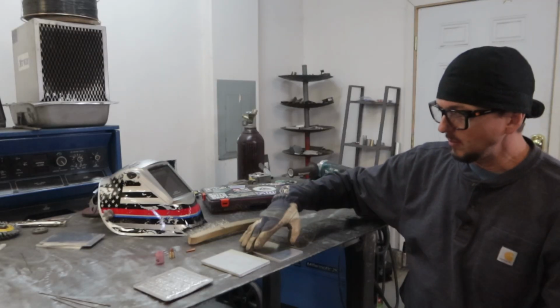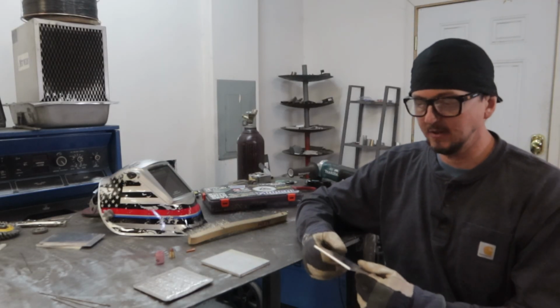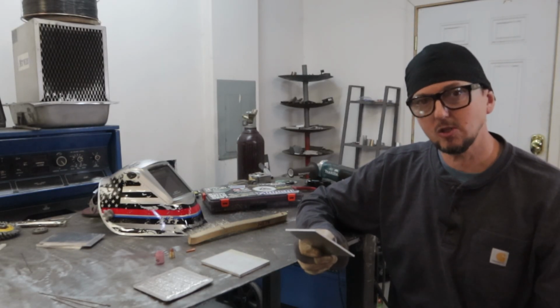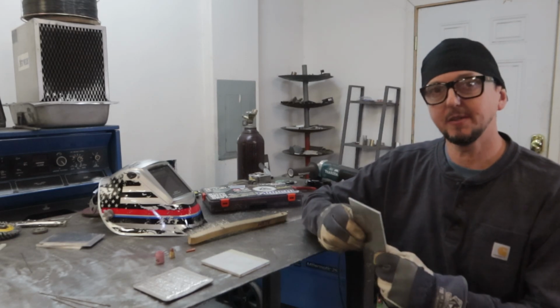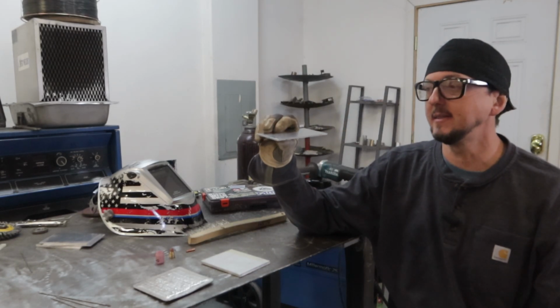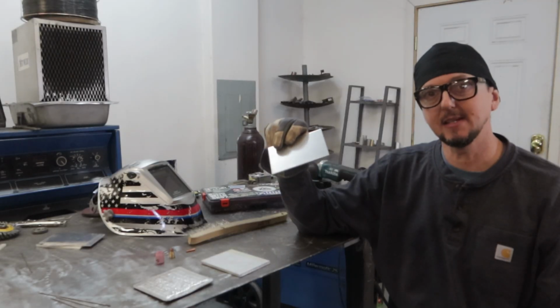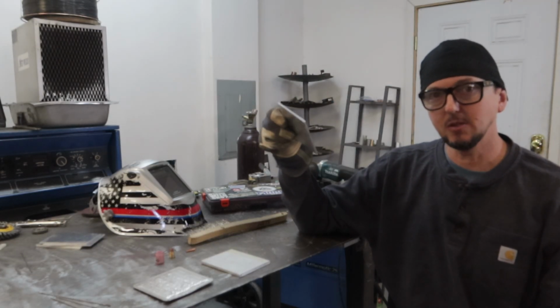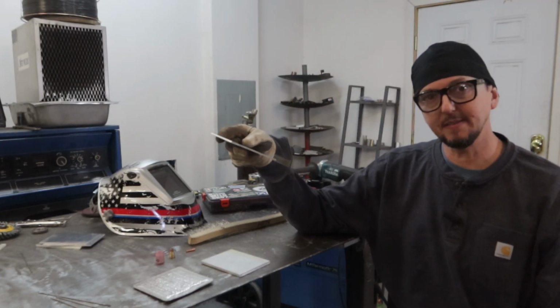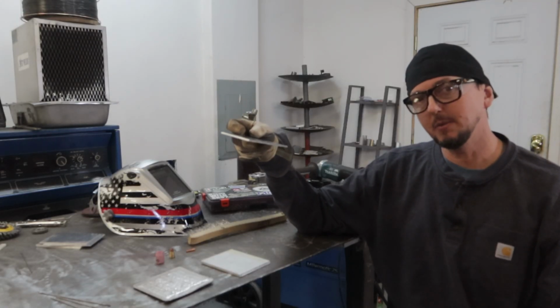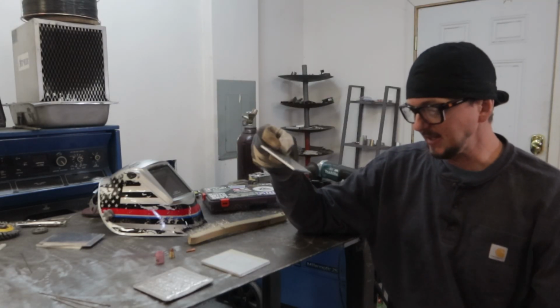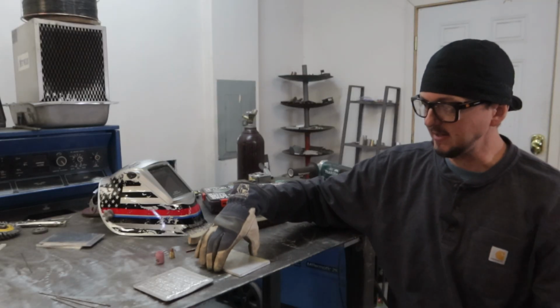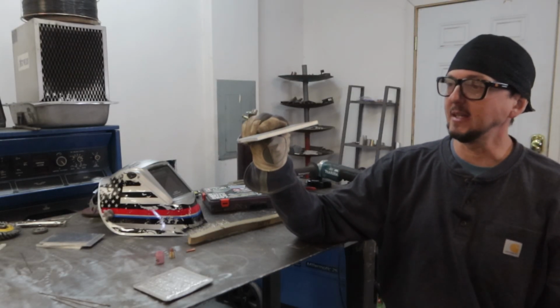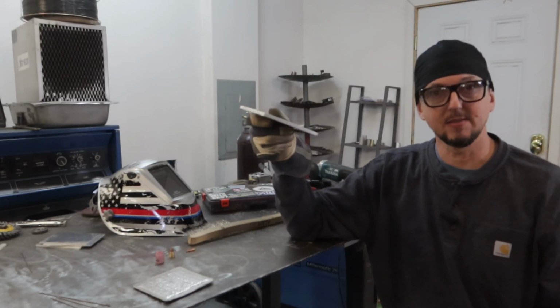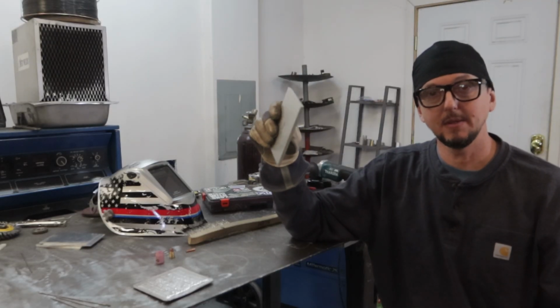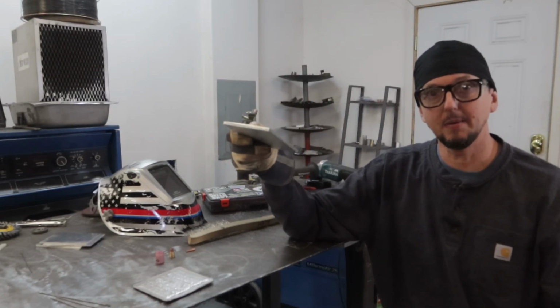So we can get a good size piece of aluminum, either 1/8 inch or higher. We want a little thicker aluminum if we can find it, because we're going to be putting a lot of heat into this material, and we're going to need to manage that heat effectively. So the thicker the aluminum, the better, without getting too ridiculously thick. So either an 1/8 inch piece on up to, this is like 3/16 or 1/4 inch. This is also good. This is a great piece of aluminum for this project as well, but it'll take more heat.